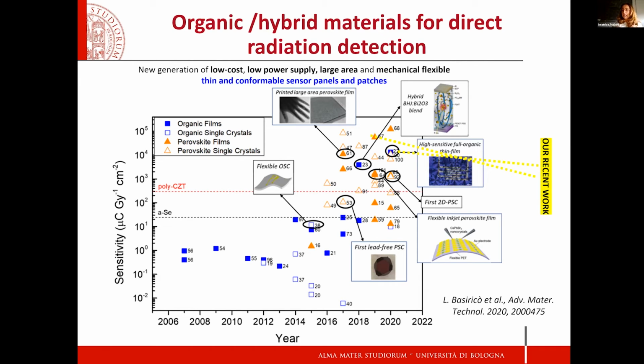sensitivity value for inorganic large area detectors based on polycrystalline CZT, cadmium zinc telluride, or amorphous selenium. So you can see very clearly that we are already way beyond the state-of-the-art with, of course, at the moment, research results, both in organic and perovskite materials.